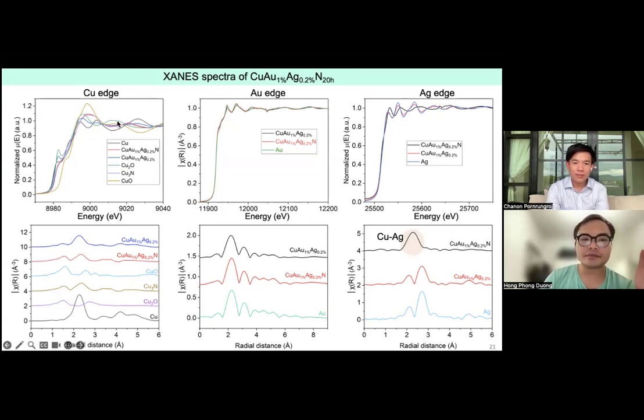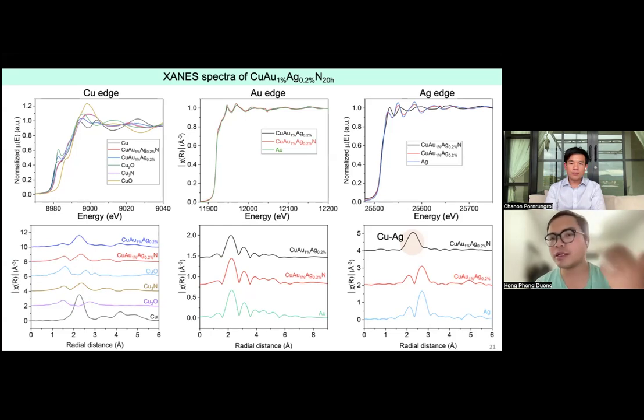But here, in the framework of TotalEnergies, we did it at the Soleil synchrotron in Paris. At least firstly we looked at the copper edge, and the copper was mainly present as copper nitride, as I'm showing here, when we performed the measurement also for the reference sample. For the gold edge, what we observed was also mostly gold bonding, as shown here. This also confirmed why we got gold nanoparticles in our sample.